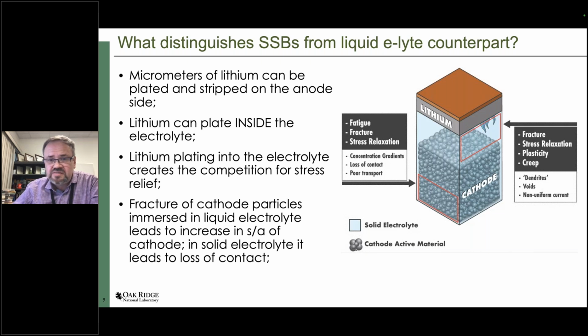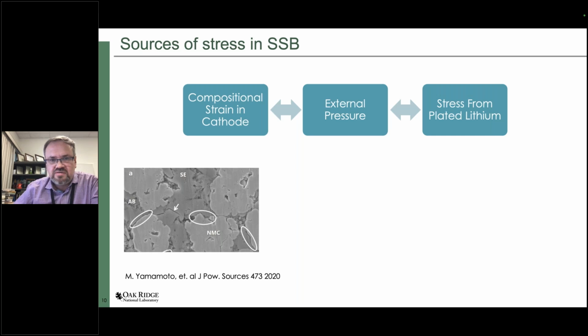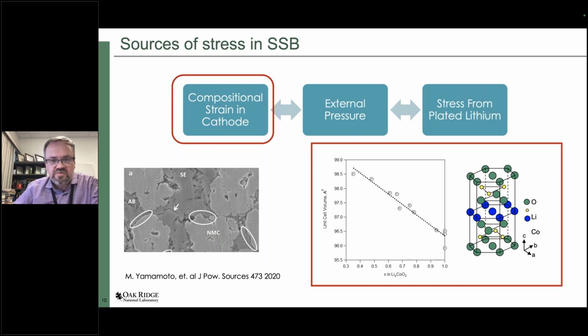So when electrochemists talk about concentration gradients, transport, cyclic voltammetry, we as mechanical engineers and material scientists hear fatigue, fracture, creep, stress relaxation, and so on, because all those processes can be connected together. And there are basically 3 major sources of stress in solid-state batteries. One is compositional strain in cathodes, which comes from the fact that whenever you intercalate or remove lithium ions into the cathode structure, which is again typically a layered transition metal oxide, you change its dimensions and its volume.